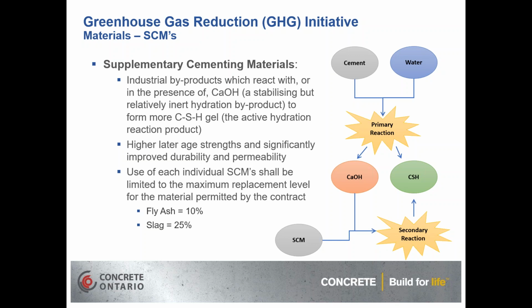Although I do believe there is a special provision out there where, for example, with slag, you could go up to 35%, but that's assuming that you're willing to do salt scaling slabs yourself for the MTO to provide them with further information on the salt scaling resistance at higher levels. So typically, you're looking at that 10% and 25% number for the fly ash or slag.